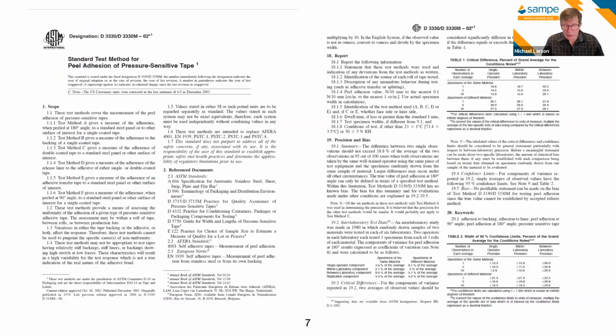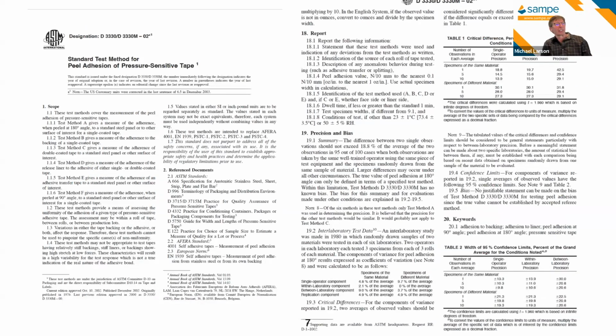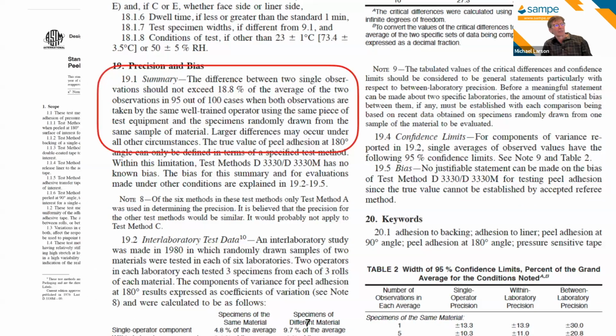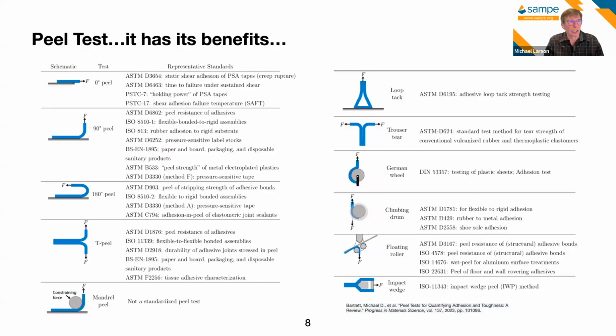The ASTM standard that is referenced there, that is commonly used for peel adhesion of pressure-sensitive tapes in particular, the working group that developed this standard, in the standard itself, of course, tells us that the difference between two single observations should not exceed 20% of the average of two observations in 95 out of 100 cases, and so on. There is a lot of variation in peel test results. And if you look at a large lot and you're trying to do everything the same, I have seen lots of variation in the actual test results. As a consequence, people have done a lot to try to modify particular peel tests to give information that may be more germane to a particular output.